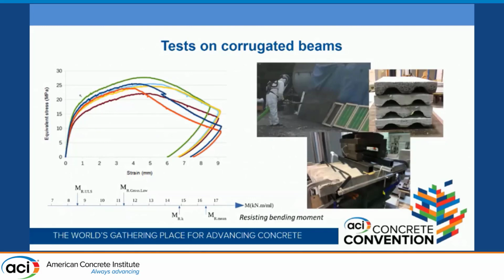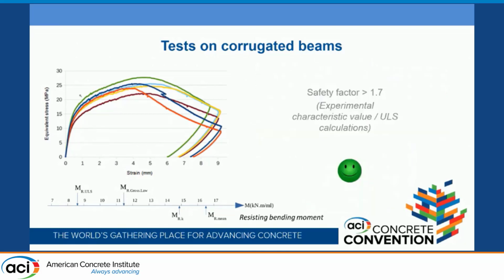We have, of course, carried out the 3- and 4-point bending tests to characterize the material. From the test results, we determine the constitutive laws to verify the sections corresponding to the shell set up in the structure. Then 12 bodies of UHPC sprayed on the corrugated sheet were tested with a 4-point bending test to determine the resistant moment. We obtain a safety coefficient higher than 1.7 by comparing the characteristic experimental values obtained on the test body and the moment calculated with the constitutive laws.